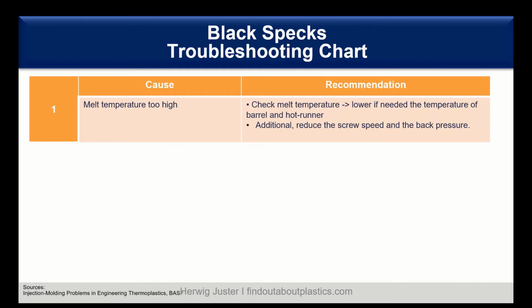Okay, how can we troubleshoot black specks now, starting with our troubleshooting chart and the first recommendation. So the first cause, we already said, temperature is a critical thing here, and in this case the melt temperature is too high. So here's the recommendation: first check the melt temperature, lower if needed the temperature of the barrel and the whole hot runner system if you have one. Additionally, you can also work on the screw to reduce the screw speed and also the back pressure.